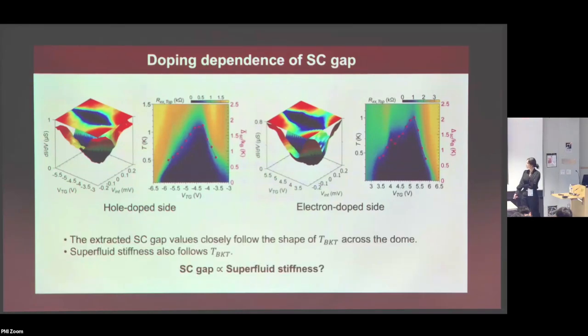So it leads to an interesting conclusion that the superconducting gap actually follows the shape of the T_BKT across the dome. And from other kinds of measurements using superfluid stiffness, we saw that the superfluid stiffness also follows the T_BKT. So this means that the superconducting gap also follows the superfluid stiffness, which needs further theoretical understanding of what's exactly going on here. But this at least once again shows you that this is the superconducting gap.